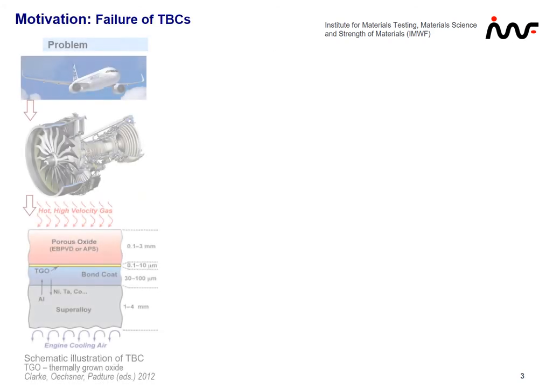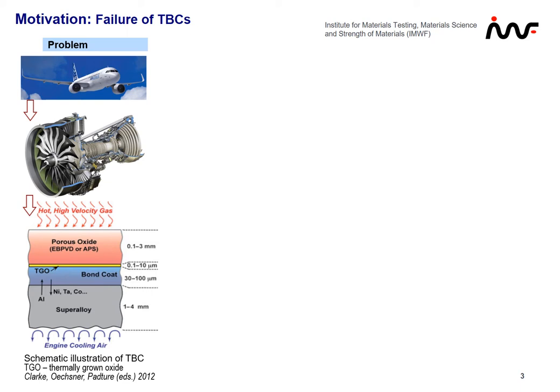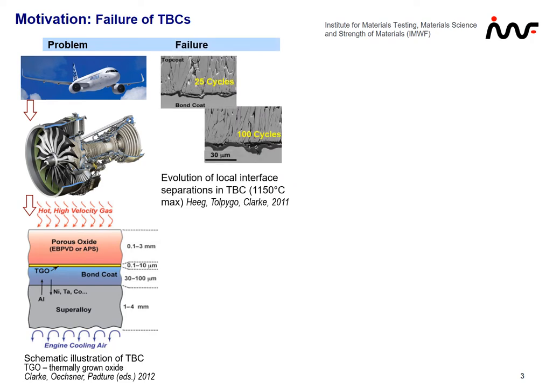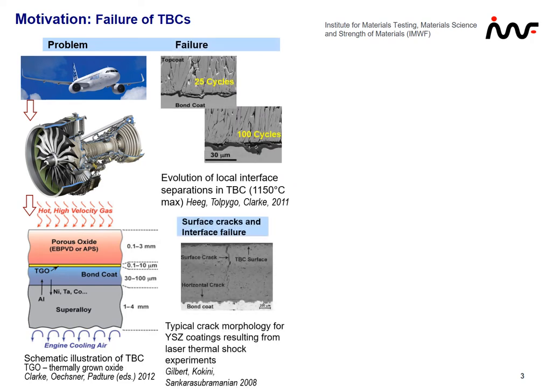Motivation. Thermal barrier coatings are used in different engineering structures. One such application is shown in this slide — in airplanes and engines. Thermal barrier coatings are used to prevent melting of metal thermal parts, and they are made mostly from ceramics. But ceramics and metals have different thermal expansion coefficients, and under the influence of thermal loading, high residual stresses arise at the interface, which cause debonding and cracking. We can see some crack patterns for such coatings.